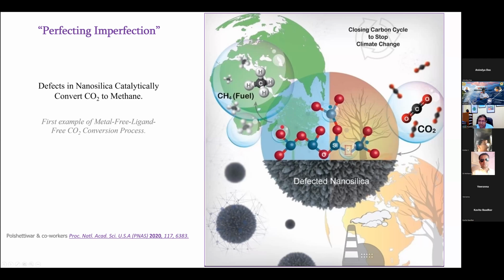So what will happen if I create an oxygen vacancy, and whether these sites, oxygen vacancies, Si radicals, oxygen radicals, will come together and work cooperatively to activate CO2 and hydrogen. And indeed, that's what we observe: if you can create the proper types of these sites with the proper proximity, they work together to dissociate hydrogen, activate CO2, and then CO2 is converted into methane. No need of any metals, no fancy expensive materials, only silica.